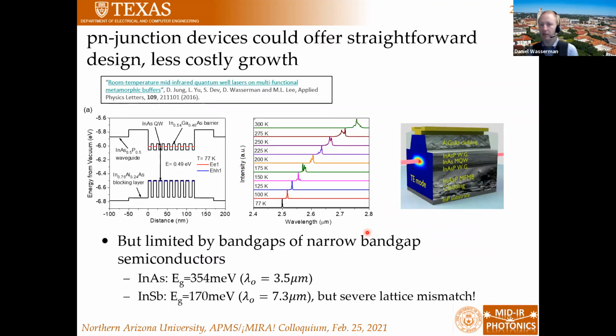So if we look at PN junctions, this is work done with my colleague Larry Lee, who's now at the University of Illinois, where we showed that you could grow indium arsenide quantum wells on an indium phosphide substrate using a metamorphic buffer layer. And we fabricated lasers out of these devices that lase at room temperature. But ultimately, these are limited by the band gap of your indium arsenide. So the indium arsenide band gap is around 3.5 microns.